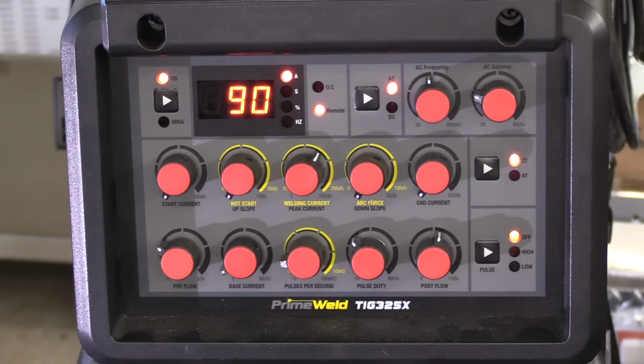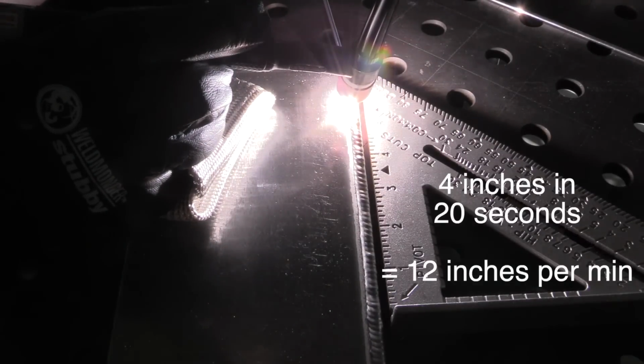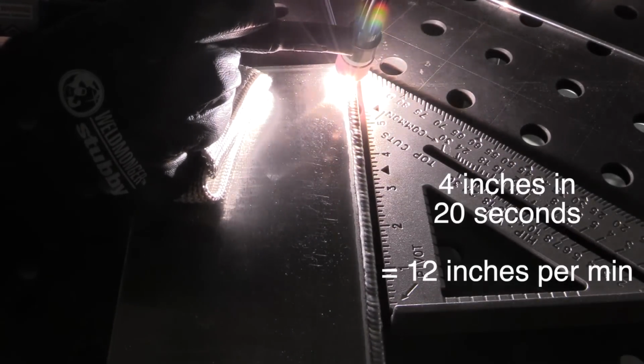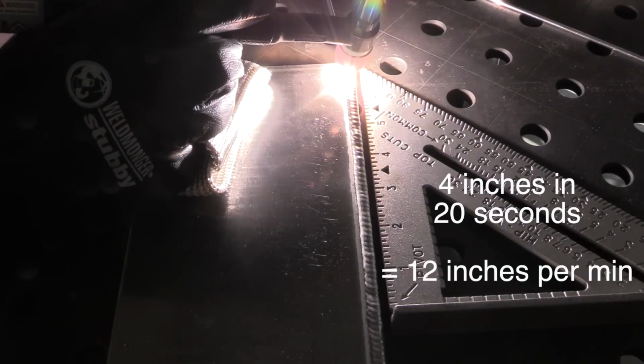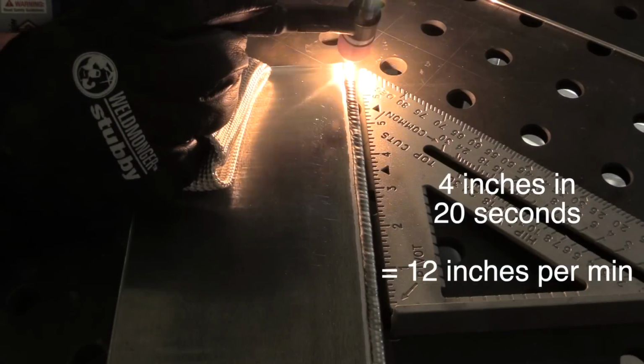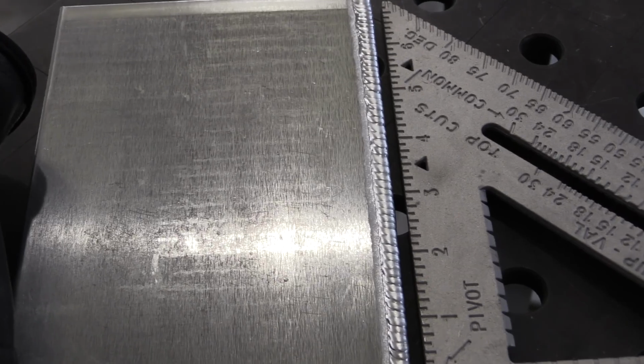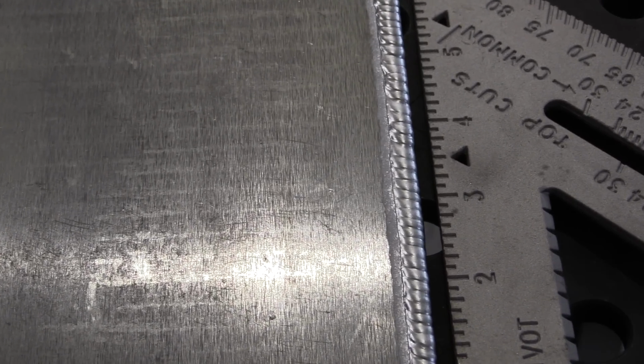So this is more like 12 inches per minute instead of 7.5. That could be a really big difference maker. The appearance doesn't seem to have suffered at all, and that's what I've found. Sometimes going a little bit faster can actually make sort of a better looking weld because you're just not really concentrating on looks. You're just really trying to motor out, and it winds up being a uniform weld.